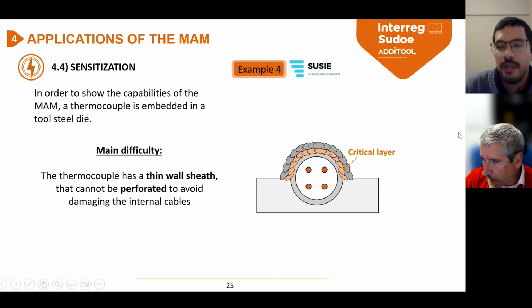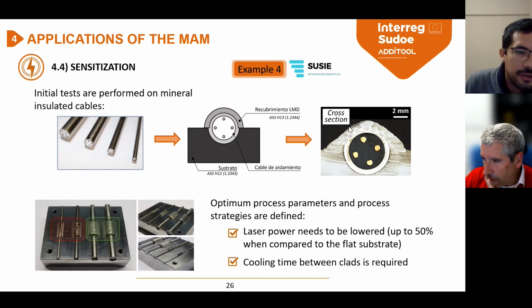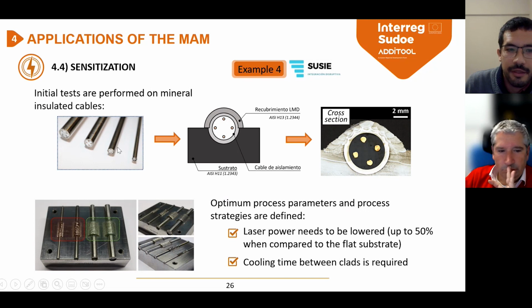In the cases we used, we performed a benchmark of the different diameters of the thermocouples, and we were able to embed even up to a 3 millimeter diameter thermocouple, and that implies a 0.3 thickness coating on its surface. So here you can see the results we obtained, and we conclude that in order to add material over the thermocouple, but without damaging the sensor, we need to lower the laser powers even up to 50% when compared to when we are adding on the flat surface.